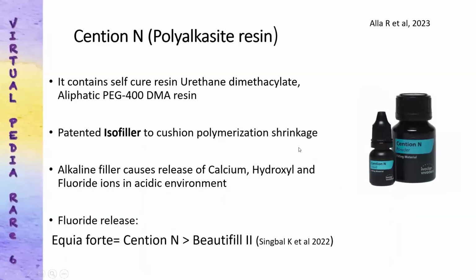Cention N is a modification of giomer. In this, they have used a different resin. It is urethane dimethacrylate aliphatic PEG 400 DMA resin. It has got patented isofiller particles which have got cushioning effect. It is an alkaline filler which causes release of calcium, hydroxyl and fluoride ion in the acidic environment. And this is the reason why this material has got good strength and it has got fluoride release equivalent to Equia Forte. The fluoride release of Cention N is higher than Beautifil 2.